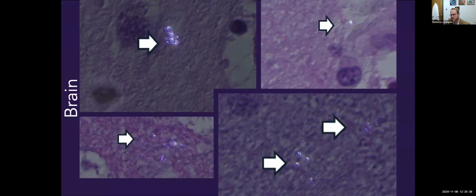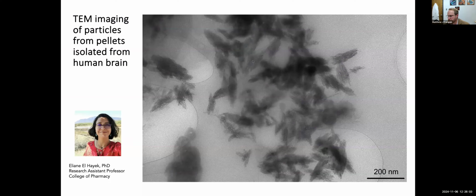The brain is really tough. The brain is interesting. We don't see those collections. We don't see those agglomerates of particles. We tend to see them as very small individual isolates, and it's actually quite difficult to find these. You'll notice there's no scale bars, but hopefully there's enough nuclei that are about 5 microns in diameter for you to sort of compare those two. Essentially, everything we see in the brain is pretty much less than 1 micron.